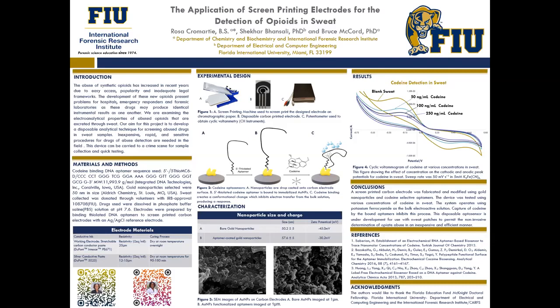And in figure 4, we have a cyclic voltammogram of various concentrations of codeine, where we can see that there is a signal drop as codeine increases. So the more codeine that is present, it blocks the reaction with the ferrocyanide, which goes back to figure 2, the end of the schematic design, where I showed you that there was a blocking between the ferrocyanide and the electrode surface. So this voltammogram shows that as you increase the concentrations, the codeine will interfere with the ability for the ferrocyanide to access the aptamer bound to the gold nanoparticle for a charge transfer exchange.